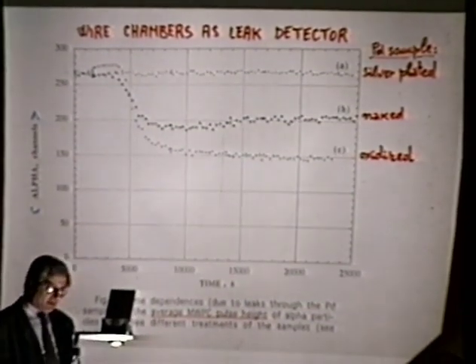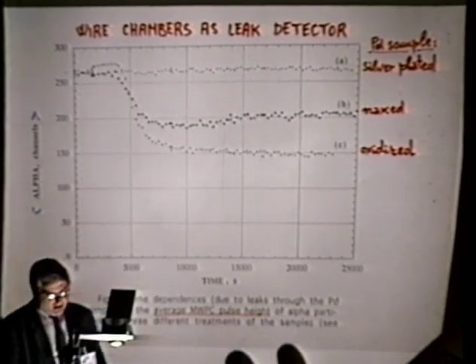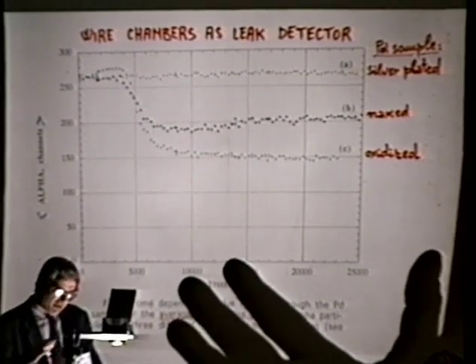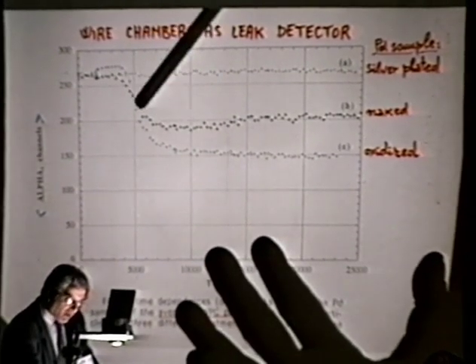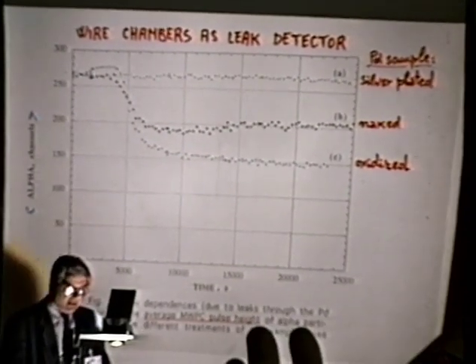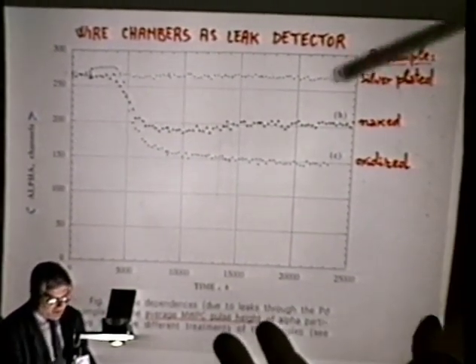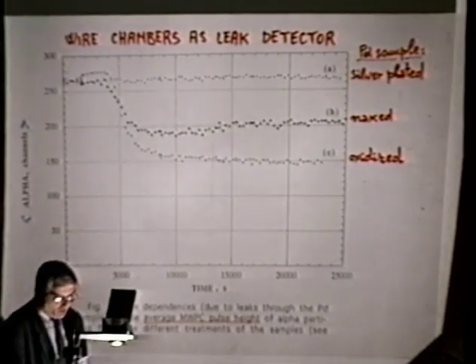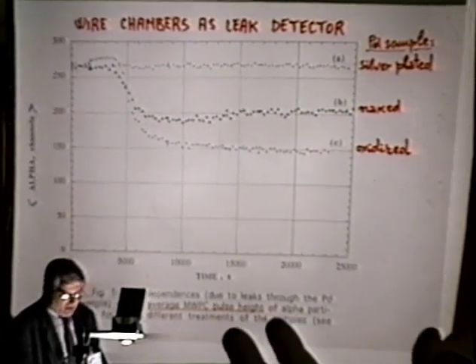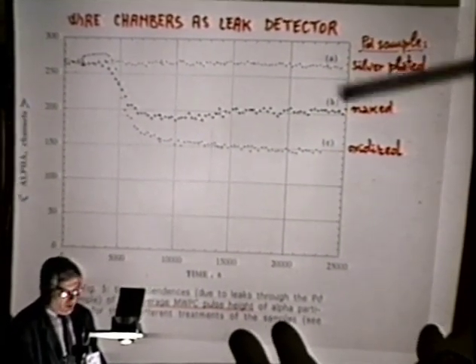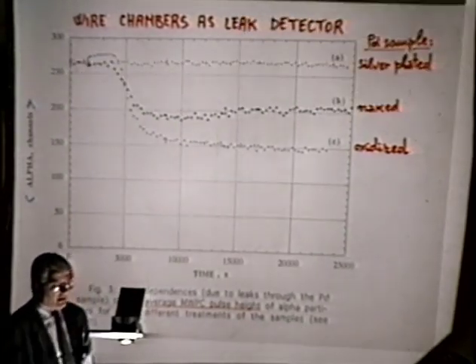So this is the average pulse height for alpha particles, and this is time. If you have a naked palladium on the side of the wire chamber, it will release some deuterium, and then the loading will be worse. So we have tried to coat this side, and with some 5 microns of silver, we had something constant here. But when the loading reaches 2/3, silver breaks and cracks, so this is not enough to reach high loading.